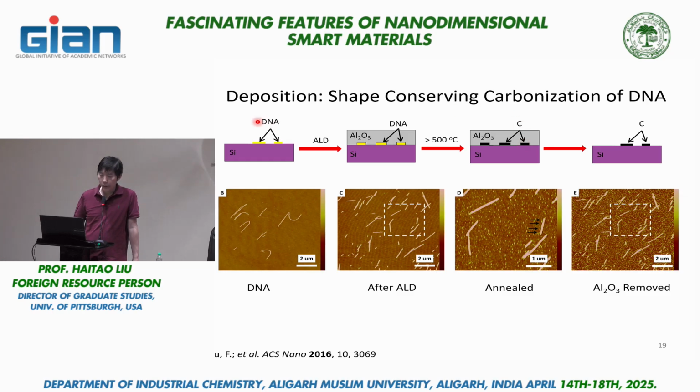So what we demonstrate here is that DNA nanostructure being organic, you can view them as feedstock. And if you coat the surface with a thin layer of oxide by atomic layer deposition, we can trap the organic material in the matrix. And once we do that, we can heat everything to high temperature and carbonize all the organic material. And that turns the DNA into carbon material. And those carbon materials are conductive, as we showed by conductive atomic force microscopy.